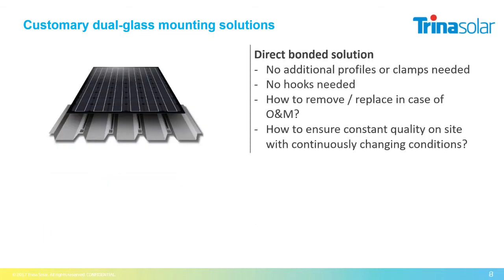Then, as a final method, there is direct bonding. In comparison to the others, direct bonding requires the lowest amount of material because you don't have additional installation rails. Here, for example, it's shown that you install it directly on the trapezoidal sheet metal. The advantage is the lower material consumption and the extremely good load distribution because you have a lot of support points. On the other hand, one of the disadvantages is what happens if the module is defective: it needs to be replaced, and because it's bonded it's much harder to remove compared to a back rail solution or hook solution.